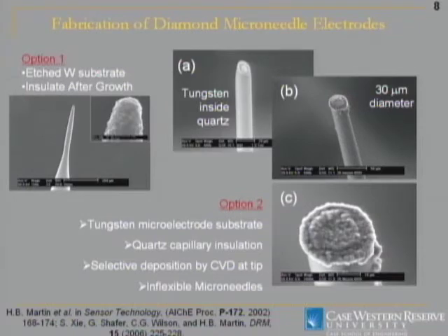We started out by tapering a wire and coating it with diamond, but then you have to insulate it afterward, which is not necessarily a very easy thing to do reproducibly. But if we mimic that carbon fiber microelectrode, we can put a tungsten wire inside the capillary and pull it and create a little disc electrode.